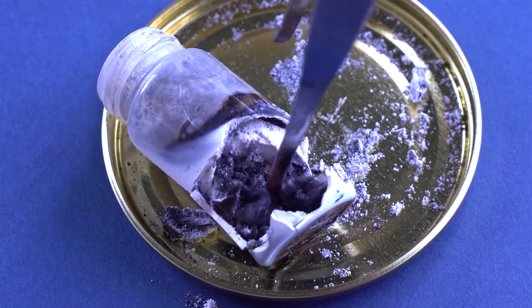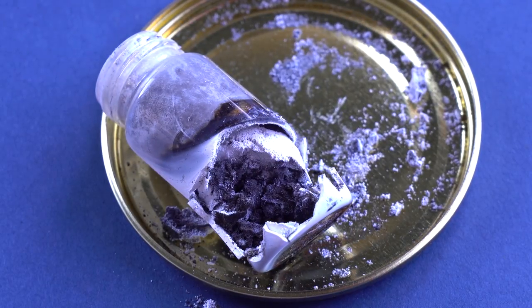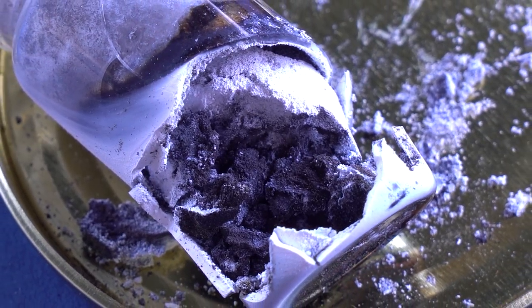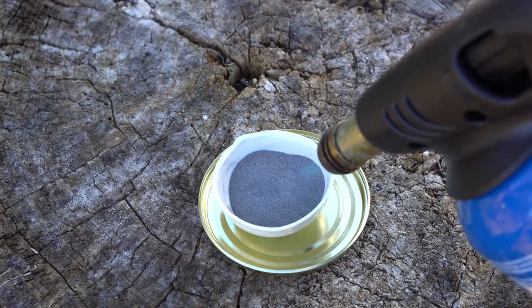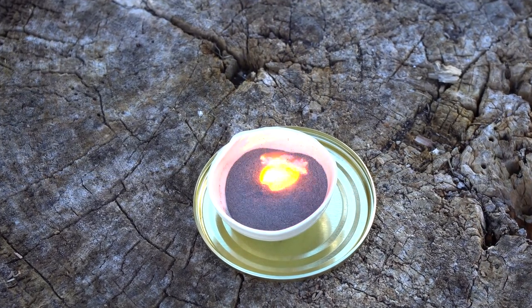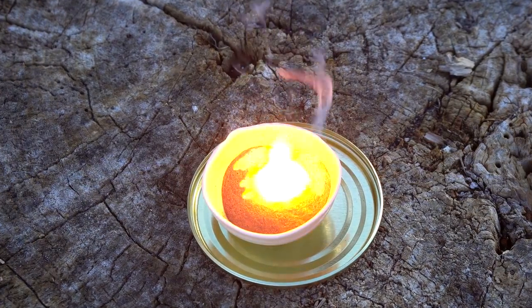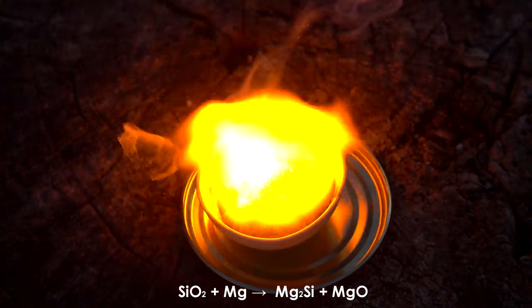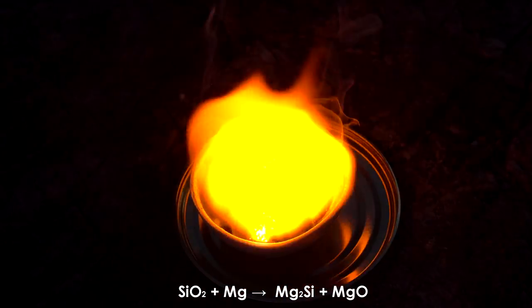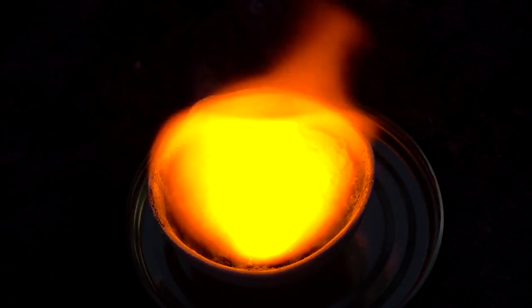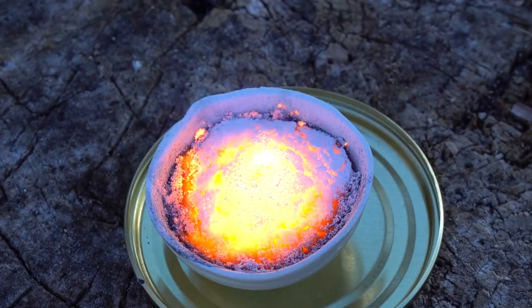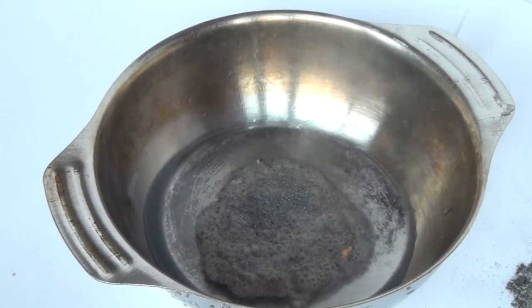This is not a very effective reaction of extracting amorphous silicon, because the product obtained as a result of the reaction can be contaminated by magnesium silicide. Besides, magnesium is very flammable in air. If we run the same reaction, but use twice as much magnesium, we will get magnesium silicide as a result of such a violent reaction between sand and magnesium powder. What is noteworthy about this substance is that when it reacts with 10% sulfuric acid, the reaction produces a pyrophoric gas silane, which self-ignites when it reacts with air.